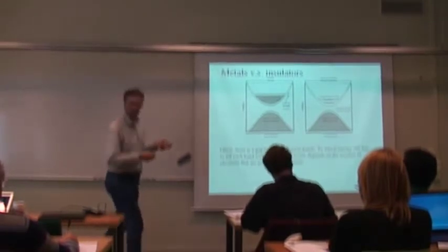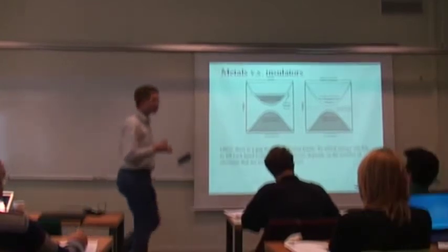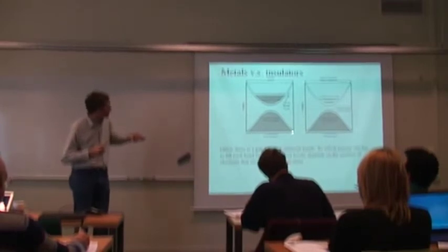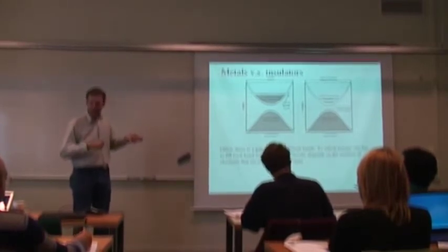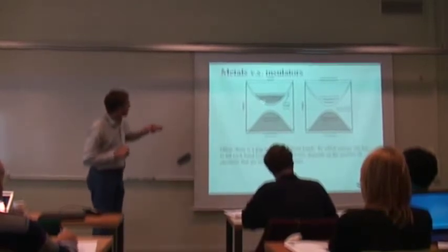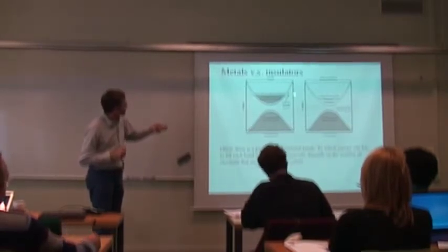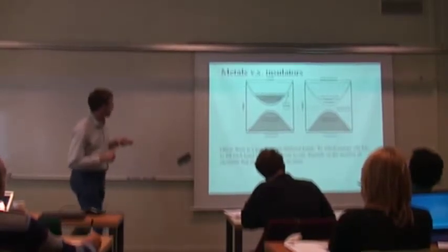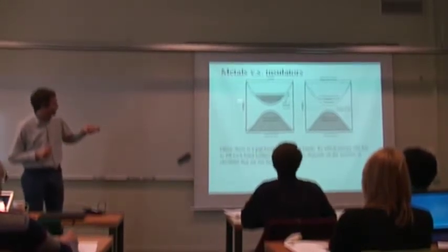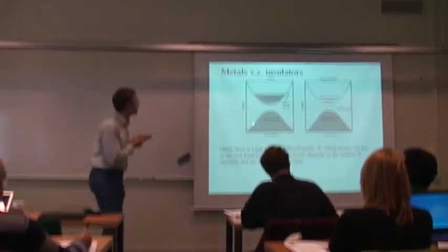So in a metal, what happens is that I figure out how many electrons I have in my system. So I fill up all these bands, and I cannot fill it doubly, so I just try to fill the lowest lying bands first, because that gives me the lowest energy. And then at some point, my electrons are gone, I don't have any more electrons to put in, and I might be in a situation like this. And to where I fill, one has to calculate, and it's called the Fermi level. So if I'm in a situation like here on the left-hand side,